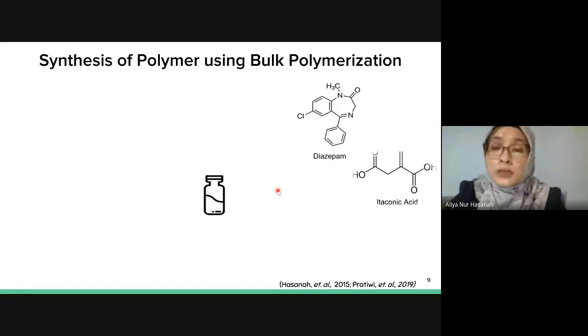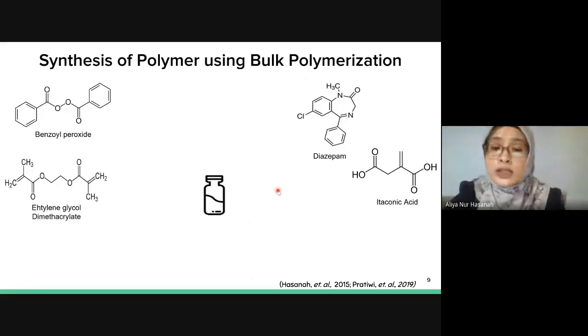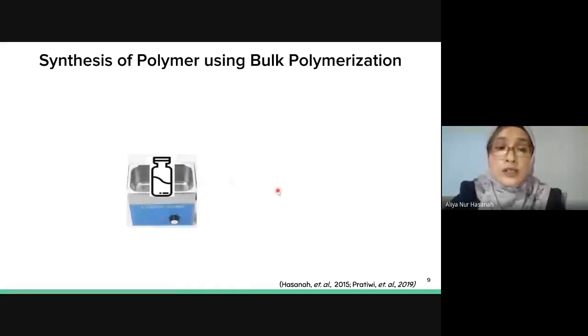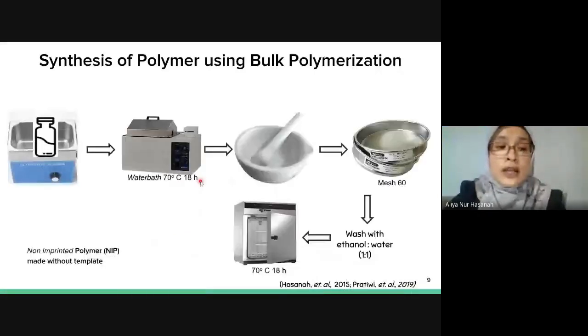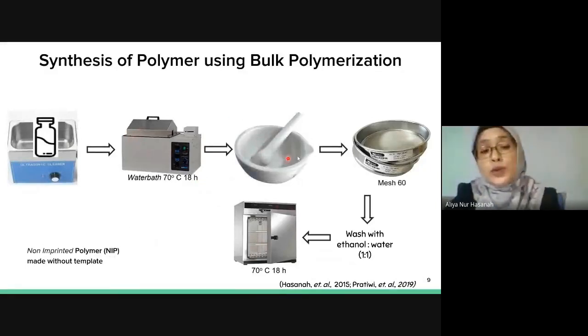We mix together all the compounds that I already explained in the file, and then sonicate to release the dissolved oxygen, and then we put it in a water bath at 70 degrees Celsius for 18 hours. After we have a polymer, we crush it, and then we filter using a mesh 60. We wash the reagents that did not polymerize using ethanol and water, and we dry them in the oven at 70 degrees Celsius for 18 hours. We also made a non-imprinted polymer.